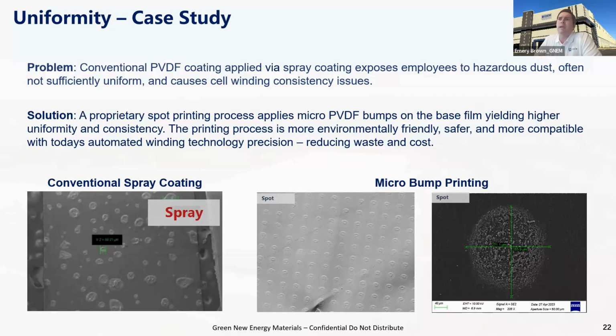I'll provide a quick case study on uniformity. One of the problems in separator manufacturing is how PVDF, the polymer, was put onto the base film. It has typically been applied through a spray coating process. Not only was this hazardous to employees, with dust and everything else, but it was a very non-uniform coating, as you see on the bottom left. This often caused cell winding consistency issues. In the past it wasn't so bad, but with today's high volumes and fast manufacturing cranking out cells, this is becoming an issue.